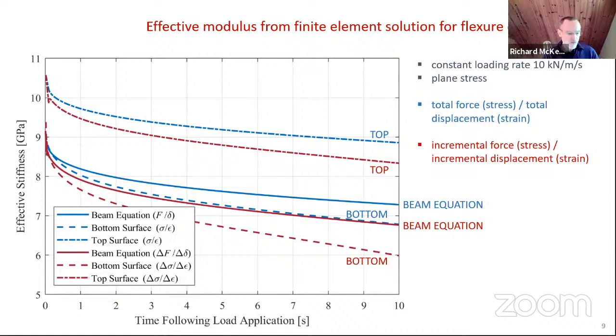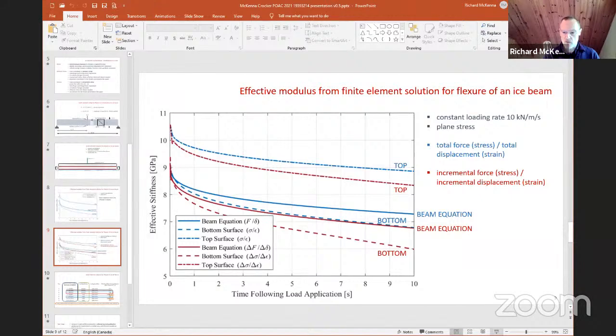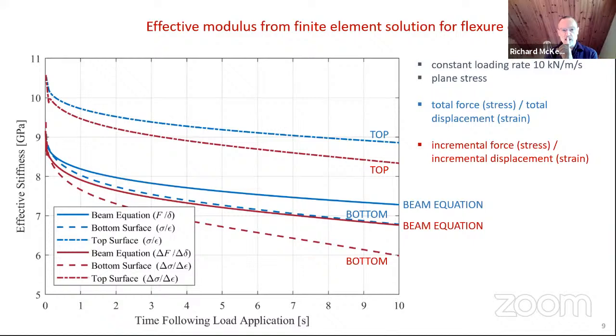And here I've got a constant loading rate, so I'm ramping up the load to 100 kilonewtons per meter over 10 seconds. So at the end of the 10 seconds, it's actually this same applied load. You can see in the blue, the top and bottom in the beam equation, I've used the total force and the total displacement, or the total stress and the total strain over that time period. And you can see at the end of 10 seconds that the result is slightly more. So the effective Young's modulus after 10 seconds is greater. It's about 7.2 there as opposed to 6.5.